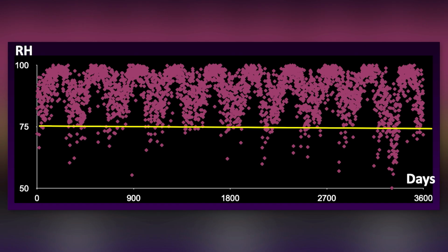It requires that humidity passes a certain threshold, so we can imagine that where we've got a brine, some salty water inside a porous stone, gradually the humidity falls and it dries out that brine. The brine crystallizes, and it's those crystals that exert pressures on a stone or a piece of masonry.